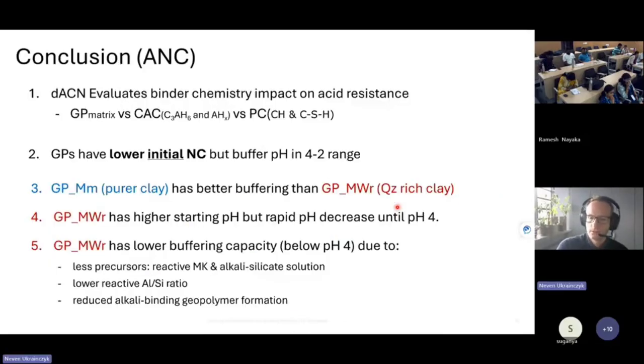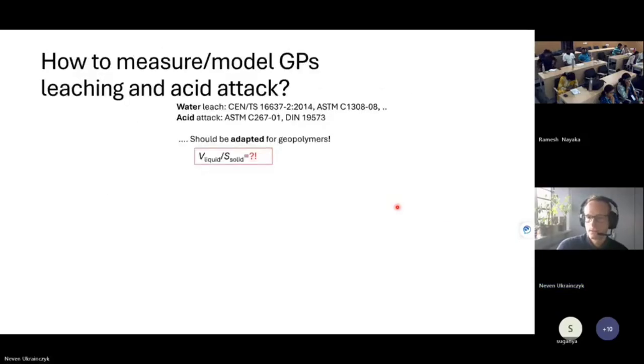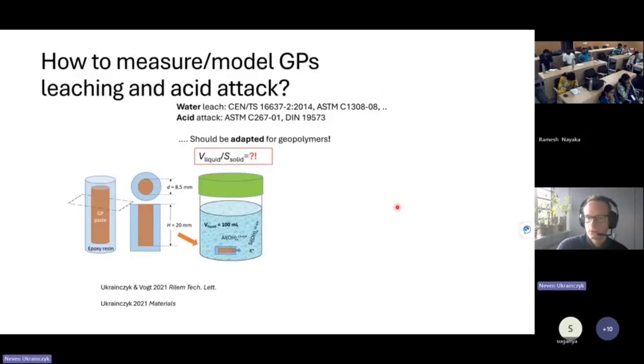Yeah, I will not read these conclusions. I will just continue with how to measure the acid attack now. I also proposed a method for how you can do the diffusion test. Also, if you epoxy coat your sample of the paste, you can then see how, with different liquid-solid ratios, you can measure the ion leaching.